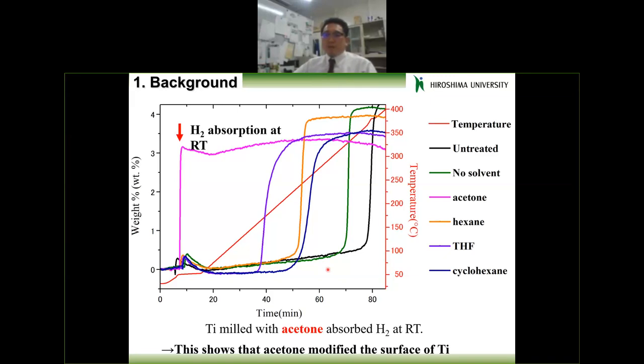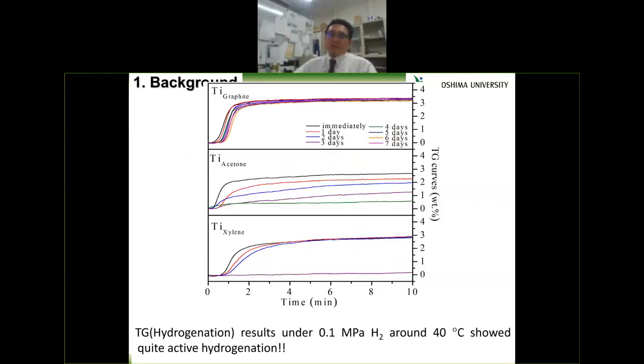But if we perform ball milling using acetone or some organic material, this is a surprising result. It shows that hydrogen absorption can be seen at room temperature. That means that by using a typical organic solvent and ball milling, an active surface can be generated, and that solvent can cover the quite active surface, and then it can keep such a quite active state for a long time. And recently, we noticed that graphite also acts as a good surface covering material.